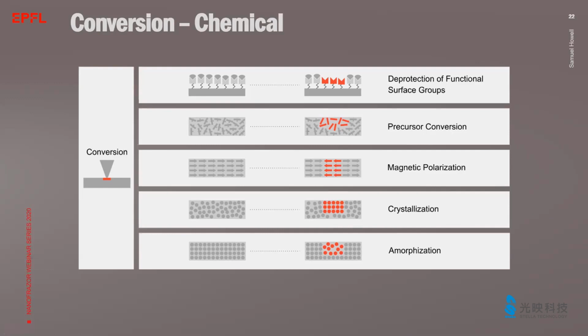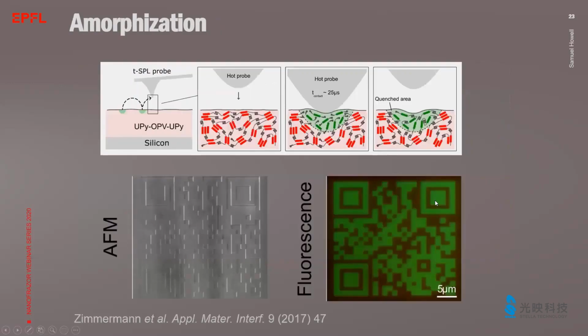Ferroelectric nanostructures have also been fabricated from sol-gel based thin films. However, these processes require rather long annealing times on the order of milliseconds to seconds. And the opposite phase transition from crystalline to amorphous is also possible. The fast heating and cooling rates attainable by TSPL enable local quenching at the nanometer scale. And here I would like to bring in a short example, an own study that we performed.